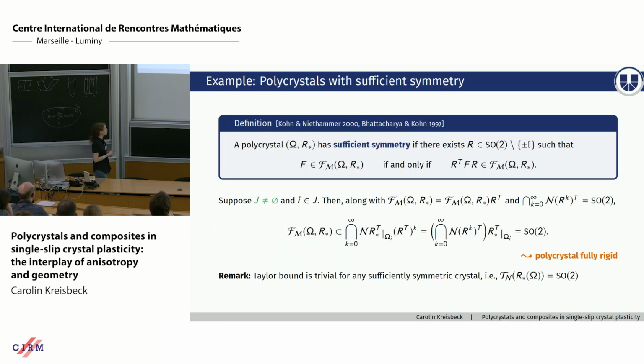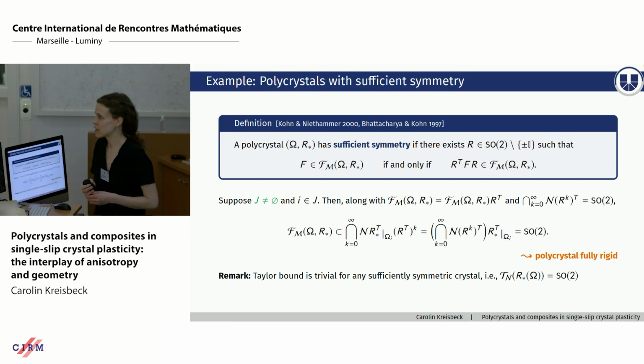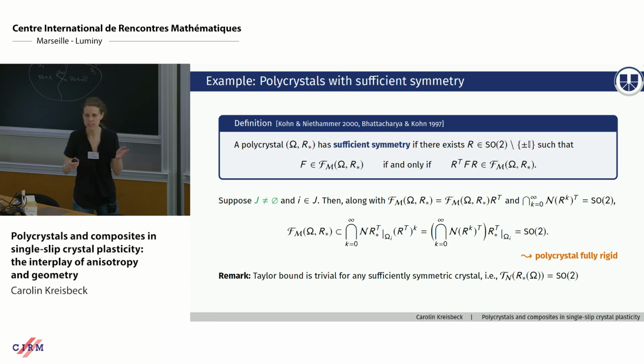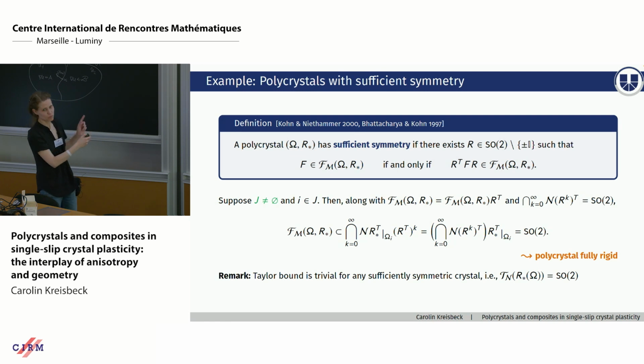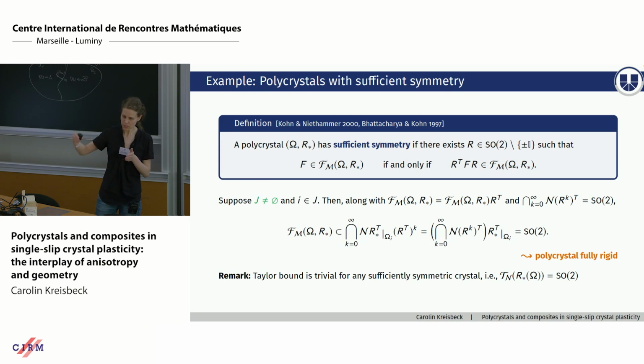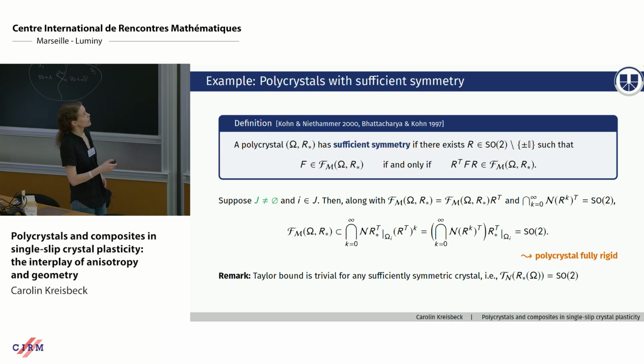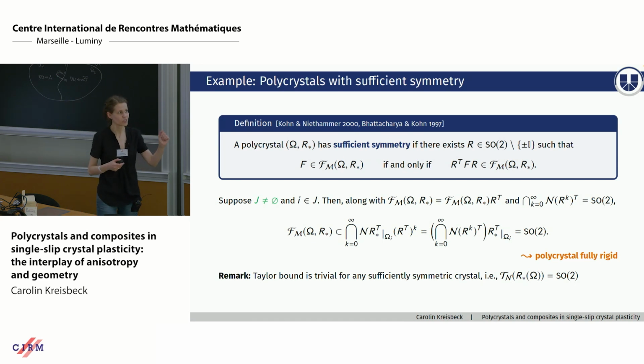Good, so now I have two examples. First one is polycrystals with sufficient symmetry. By sufficient symmetry, we work with the notion in these two papers, saying that essentially the set of attainable macroscopic deformations is invariant under a certain orthogonal transformation. If we then have a green boundary grain, so remember the previous slide, then we can apply this symmetry condition iteratively and in that way show that SO2 is an outer bound on our set Fm. Okay, if SO2 is an outer bound, then the polycrystal has no option other than being fully rigid.